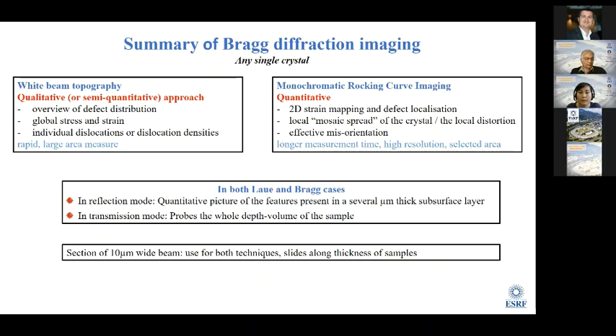Both techniques we can do in two modes, either reflection mode or transmission mode. For the reflection mode, we can have the information of either the substrate surface or the core layer on the substrate. And in the transmission mode, we can probe the whole volume of the sample.